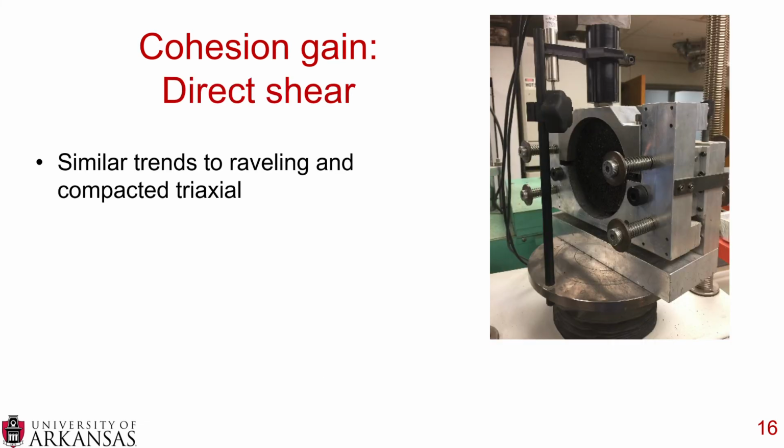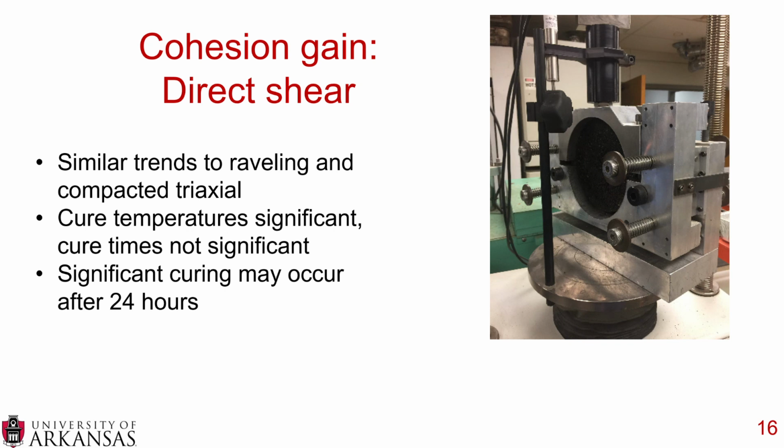And finally, the cohesion gain with the direct shear. We found similar trends to both the Raveling and the compacted triaxial test. We did find that the cure temperatures were significant, the cure times were not significant, and we did find that significant curing may occur after 24 hours.